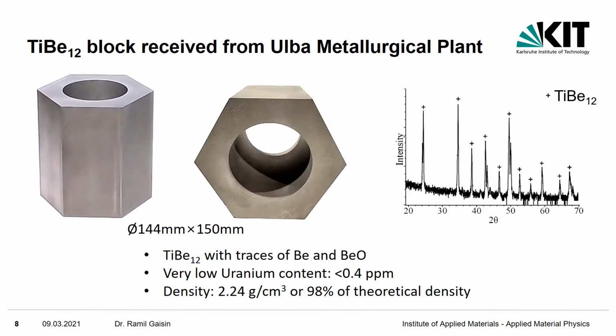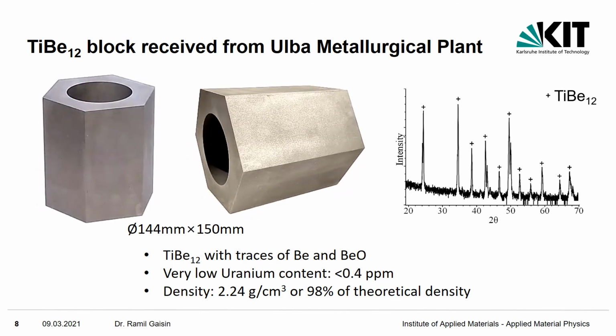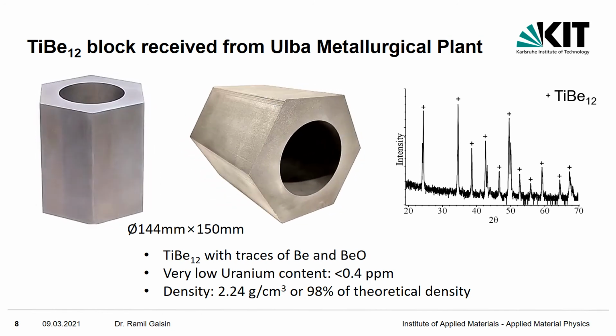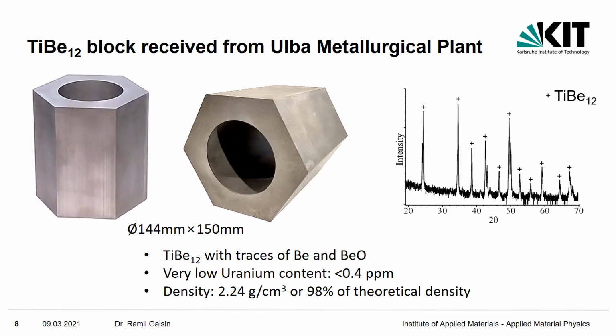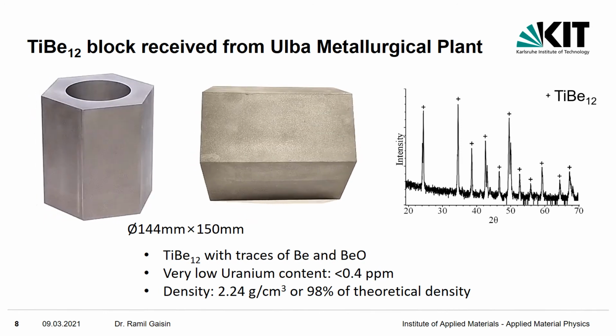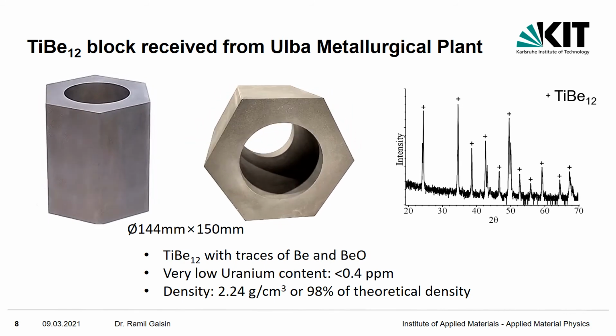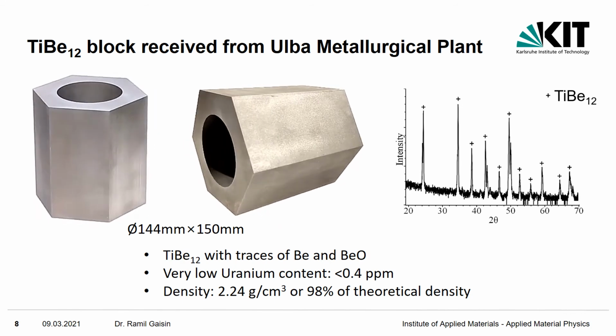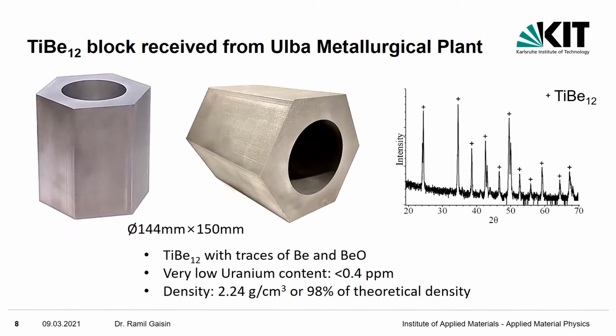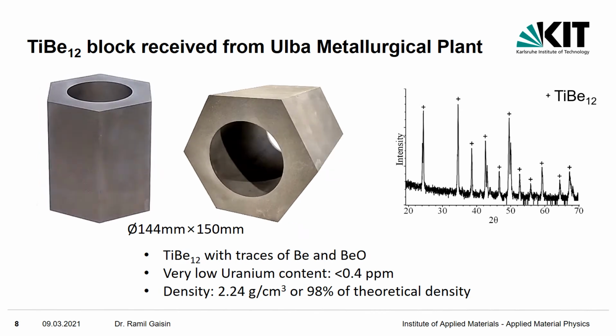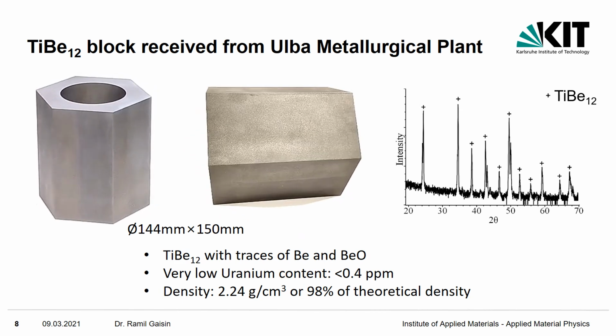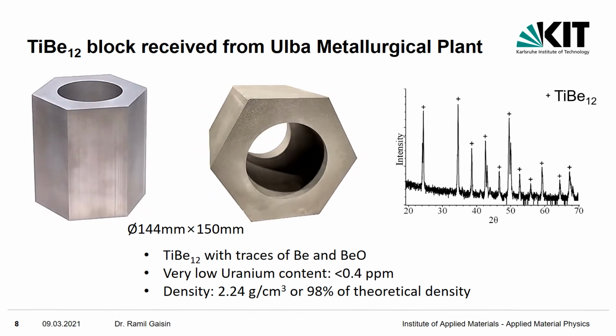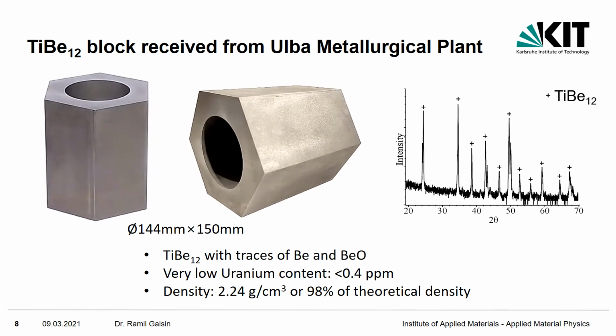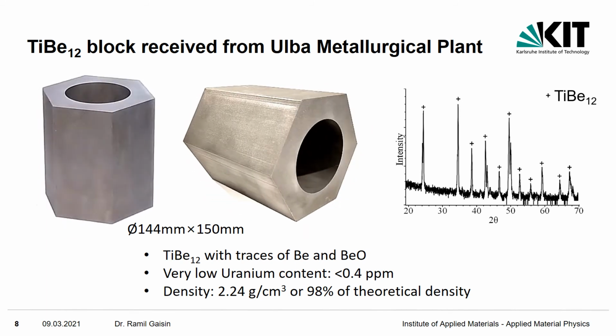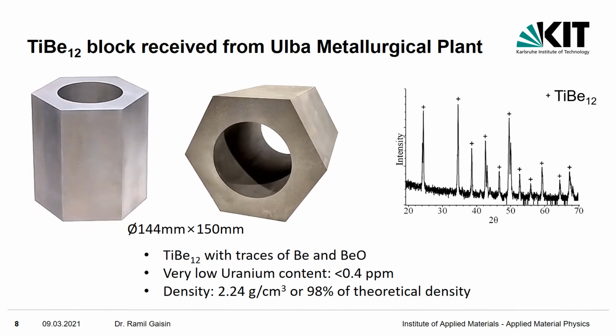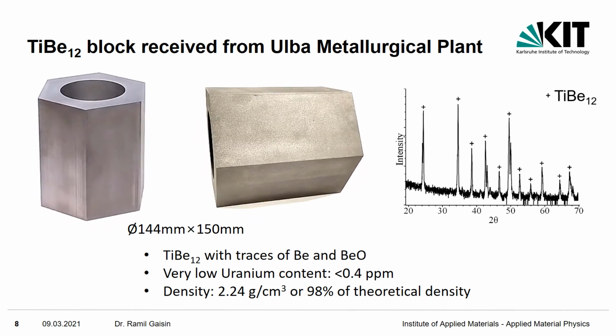At the moment, several blocks of titanium beryllide have been manufactured in industrial conditions using industrial equipment in the Ulba Metallurgical plant. They have hexagonal shape with a central hole. They are quite large, with 144 mm in diameter and 150 mm in height. The material is almost single-phase titanium beryllide with only traces of beryllium and beryllium oxide. The material has a very low uranium content, which means there won't be long-lived isotopes after working in a fusion reactor. The obtained beryllide is a quite lightweight material with a density less than that of aluminium.